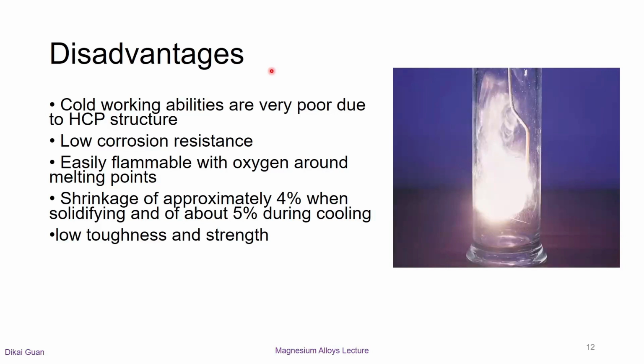On the contrary, magnesium alloys have several disadvantages, which strongly hinder their applications in several industry sectors. The biggest scientific issues are poor cold working ability at room and lower temperatures because of its HCP structure, and poor corrosion resistance, which causes safety risk when the component is in service in hot or humid environments. Magnesium is highly flammable when the temperature is around the melting point, and magnesium burning produces a large amount of heat. During solidifying and cooling, shrinkage can easily be introduced. Finally, it has low toughness and strength, which makes magnesium alloys not competitive with aluminum alloys.